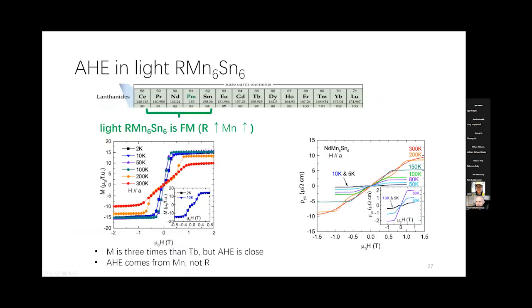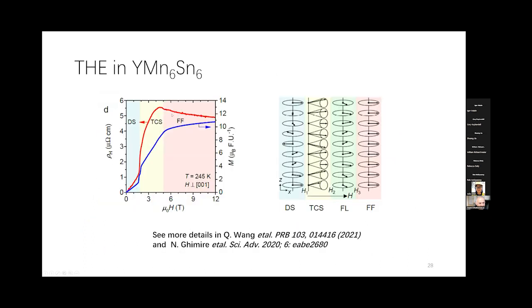We also measured the light rares. Basically, it's ferromagnetic, but the anomalous Hall effect is the same as the ferromagnetic one. That indicates the anomalous Hall effect basically comes from the manganese atoms, not from rare earth atoms. So this is a work for the non-magnetic. We notice it also has a very strong topological Hall effect in yttrium 166, but that's another interesting story.